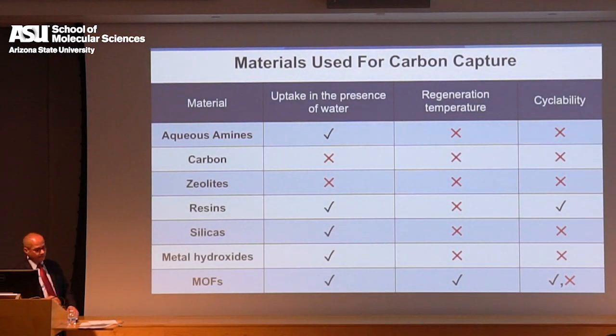So where are we in the carbon capture world? Okay, we are here. There isn't an ideal material right now. They all have problems. The aqueous amines, which have been used for 100 years to separate CO2 from methane in natural gas mining, are problematic because the regeneration temperature is high, 120 degrees. They're not very cyclable, can't cycle too much because they decompose and they become environmental problems, and amines are corrosive. They're liquids, they're water, they are aqueous amines, and the heat capacity of water is high. So frameworks may be better, or solids better, because they have lower heat capacity.